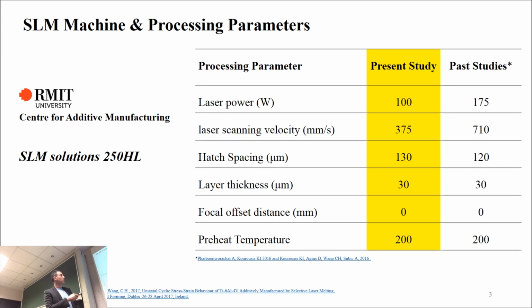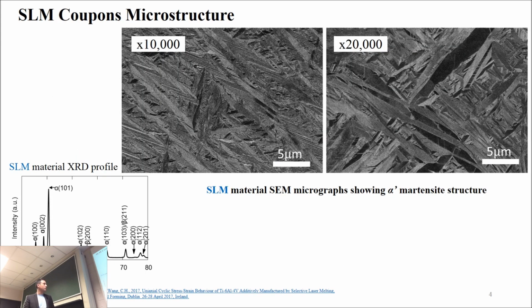What came out of some preliminary SEM analysis we did is that this is not the typical wrought metal microstructure. We have seen the alpha acicular martensite structure very evidently, and the titanium 64 is heavily in the alpha microstructure regime rather than the typical wrought metal.